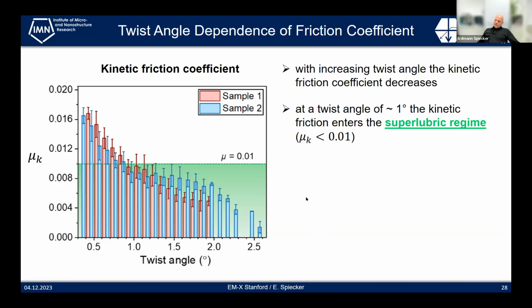No, I don't think it's mainly graphene. The principle should work for many different situations if you reach incommensurability. And we are currently talking to colleagues from mechanical simulation to also make simulations of the situation. It's just that we are most familiar with graphene. We also started to perform experiments in MoS2. From the experimental point of view, it's maybe even easier to do this for MoS2. And of course, if you make a heterostructure, you may also have a misfit between the lattice constants, which can help again to get an incommensurate structure, because you do not have to rely only on the twist, but already the heterostructure has maybe an incommensurate relationship between the two films. It would be very interesting now to apply the same concept to heterostructures. Yes.